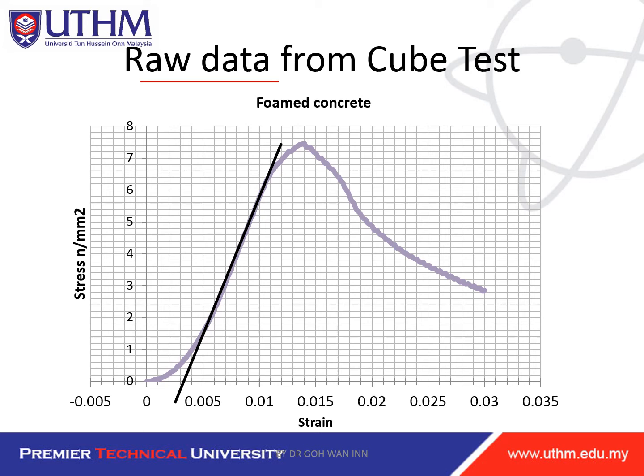Looking at this set of data, you can see the stress and strain axes. The trend should ideally go from a straight line increasing then transitioning to plastic behavior, then reaching ultimate load and softening. The initial irregular part is due to errors and imperfections — the cube surface is not perfectly smooth or straight, and there are recording errors. So once plotted, we need to remove those errors.